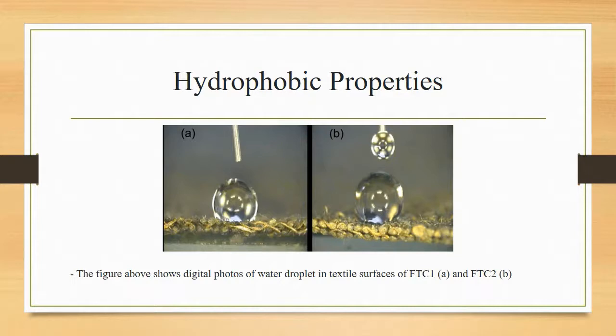However, when the coating layer was applied, the morphology of textile fibers was changed to rough in conjunction with a reduction in surface energy. This is due to the wrapping of the coating layer on the surface, which changed their surface morphology, and the incorporation of silane-based material in the coating layer. This results in good hydrophobic behavior of the surface of FTC1, which achieved a 125-degree water contact angle and 145-degree water contact angle on FTC2. However, when AP increased and the titanium dioxide nanoparticles in the coating layer, failure in hydrophobic properties in FTC3 and FTC4 samples was observed. This might be due to the change in surface morphology and surface energy of the textile fiber surface.